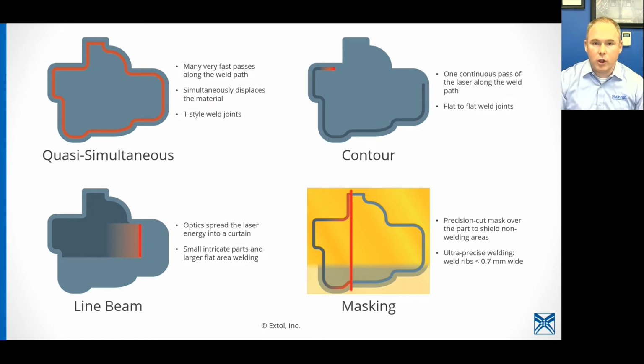Contour welding is usually used for larger parts, maybe an XY gantry, where the laser beam is physically moved, and it's got some benefits to size. But from a challenge standpoint, you can see that the beam goes around, and by the time the laser beam gets back to the starting point, it's cool. So you don't get this uniform advance of the part. It kind of needs to step a little bit. So this can be tricky to make sure you've got good intimate contact for contour welding. Line beam is where we optically manipulate that beam, kind of like a paintbrush, as we say. This is good for microfluidics often and for smaller parts in some cases. And if we need to go less than 1 millimeter, masking is a good way to do that.